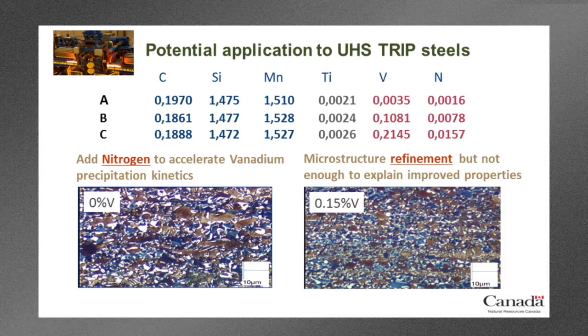So here we have some of the alloys that we actually cast, A, B, and C in this case. We had a reference heat A with no vanadium in it, and we had heats B and C where we added 0.1 and 0.2 vanadium. There was also another heat which I'll be using further on which had 0.15 vanadium, but it's basically the same base composition. There is nitrogen in these alloys as well because we wanted to see what effect nitrogen additions would have on the precipitation of vanadium carbides, carbonitrides. The titanium is given. It's residual titanium, we didn't add it, but it is important because vanadium precipitation is strongly influenced even by residual levels of titanium in your steel.